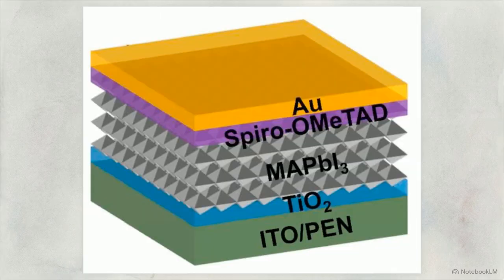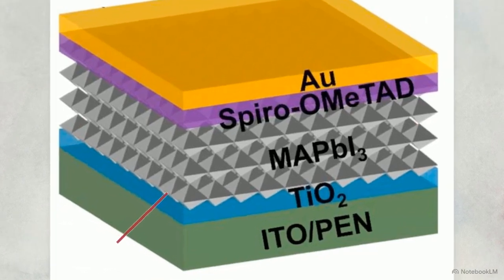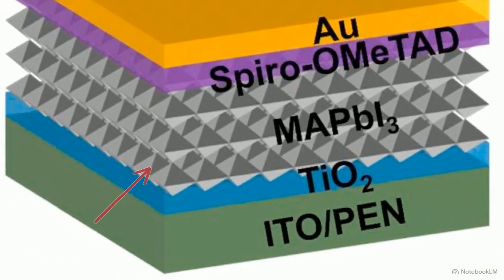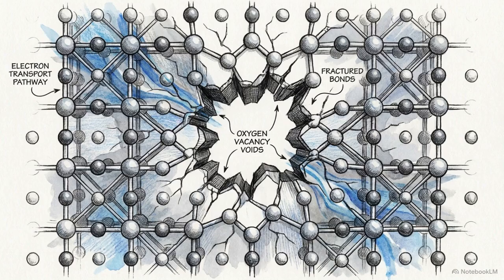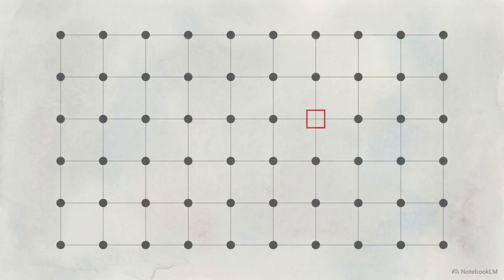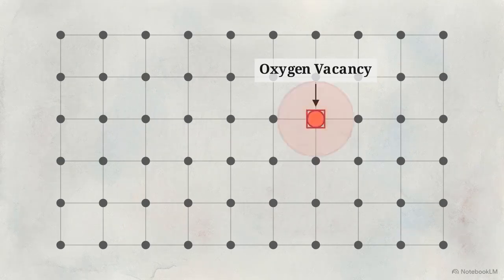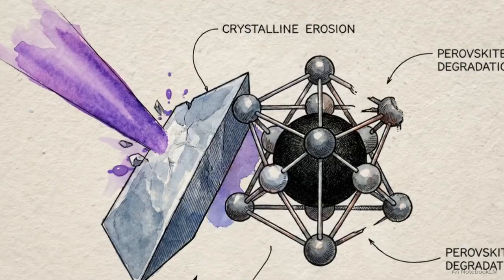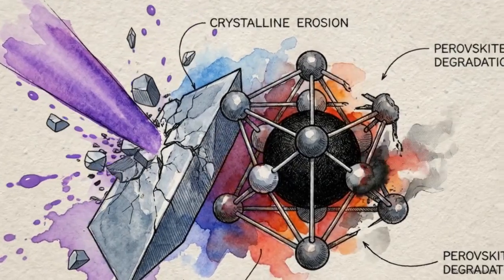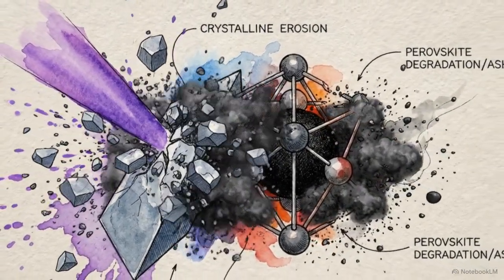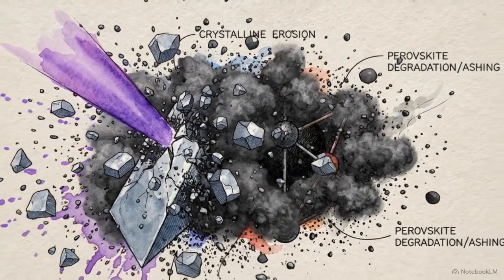Here is a 3D schematic of the physical device stack. The blue layer directly beneath the gray perovskite is the Electron Transport Layer, or ETL, traditionally titanium dioxide. The jagged boundary where these two layers meet is a primary failure point. Legacy titanium dioxide possesses high electron mobility, but it suffers from natural structural flaws, specifically oxygen vacancies. These empty spaces in the atomic lattice act as the physical traps we saw in the energy diagram. Furthermore, titanium dioxide is highly photoactive. Under ultraviolet light, a photocatalytic reaction triggers, actively destroying the perovskite structure positioned above it.